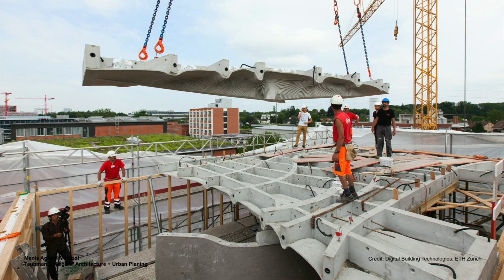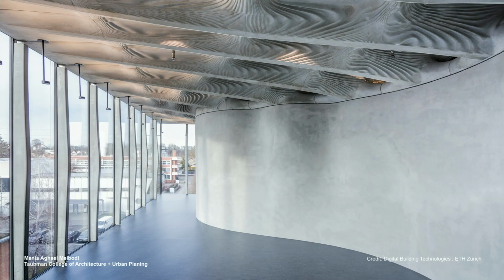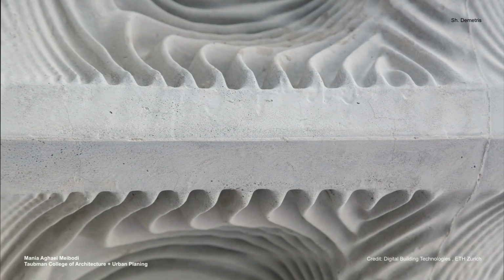Here you see the assembly of the concrete segments on the site. Assembly took only 3 to 4 days. It was quick because everything was very precise. You see how thin the slab is in most parts. The slab weighs basically 60% less than a normal slab that would stand there instead of this one. You also can see the voids that are prefabricated for sending the wires and the pipes throughout the slab. This is the ceiling side of the slab, with very filigreed concrete details, which also express that we really reached the limit of what we can do with concrete and 3D printing.